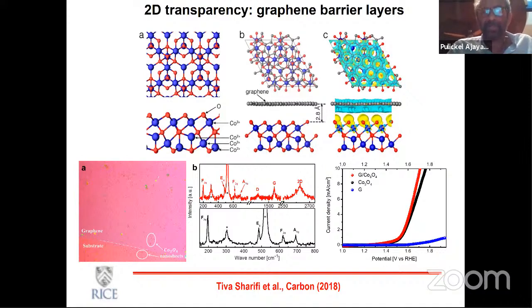In this particular case, we covered this cobalt oxide, which is a catalyst for oxygen evolution reaction. And the properties of the Co3O4 remained unchanged when you had a complete coverage of these structures with a single layer of graphene. So the point is that because of the thinness, charge transfer and behavior like that could exist even through a completely uniform overlayer, which could have really spectacular outcomes. For example, you could protect things from oxidation, still preserve substrate properties or surface properties, and so on and so forth.